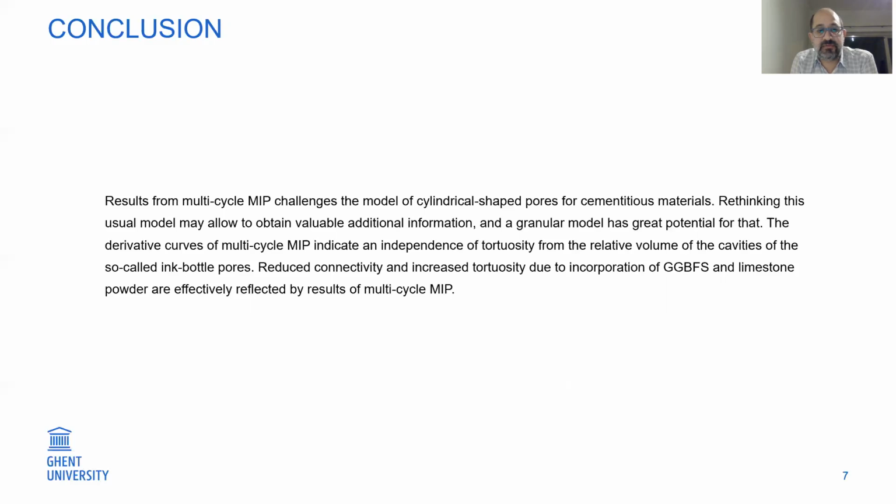Moreover, the derivative curves for multi-cycle MIP indicate some independence of tortuosity from the relative volume of the cavities of the so-called ink bottle pores, and the reduced connectivity and increased tortuosity due to the incorporation of GGBFS and limestone powder were effectively reflected by the results of multi-cycle MIP.